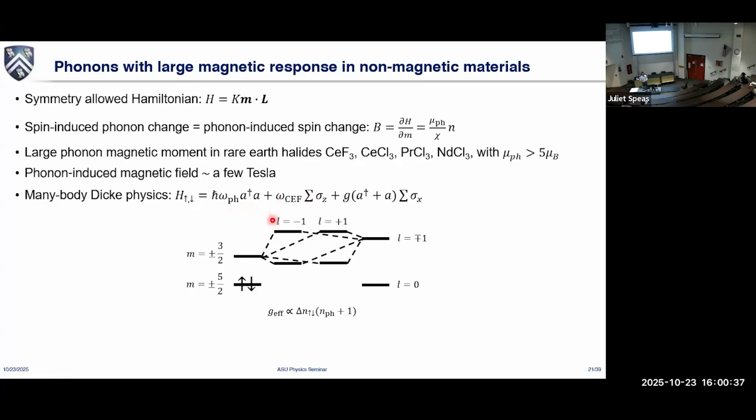So what happens is that the effective coupling is actually pretty strong, proportional to the number of your spin up or spin down electrons, which is very dense in the material, and proportional to the bosonic population of the phonon. And most importantly, it has a vacuum coupling. That is, even if there is no phonon excitation, you have finite coupling. And if you have more phonons injected, you have more coupling. So that effective coupling between the many, many electrons and the phonons would mean that they form some perturbation.